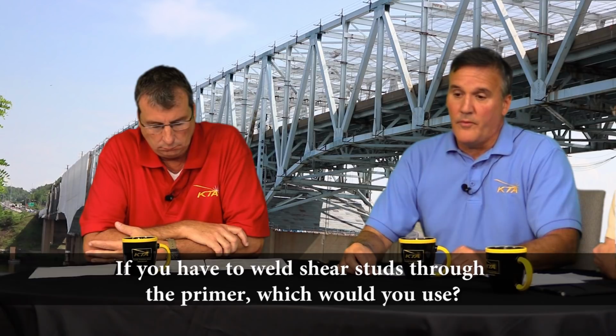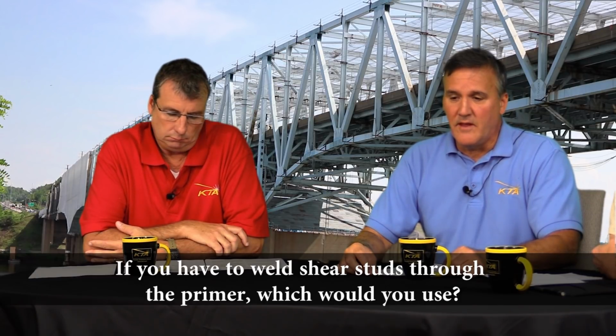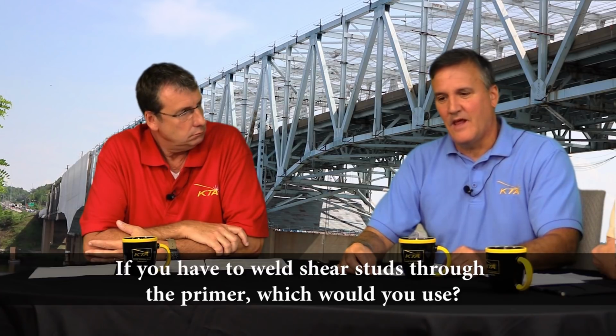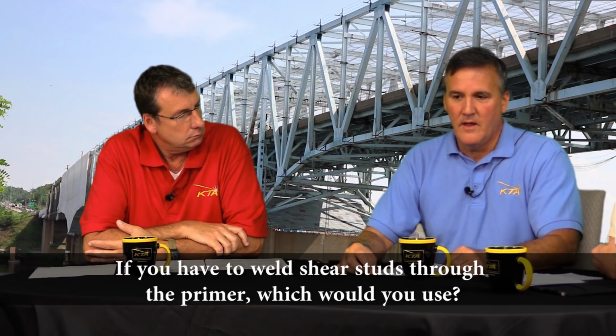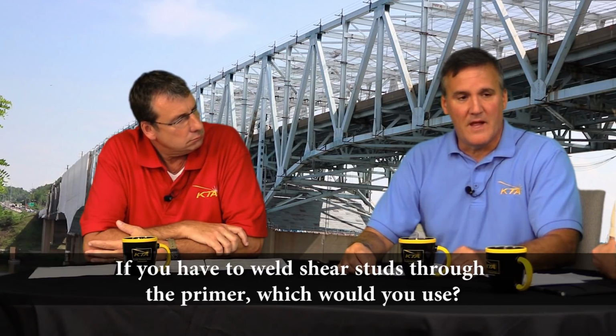Okay. All right, let me go to top flanges. Many times for bridge steel, you're going to put the zinc on the top flange only, and they want to put shear studs, attach shear studs. Which primer would you suggest in that case? Jim? Well, we see use of both, but a lot of it has to do with the sequencing of the work. If they're just exposing the top flanges and they're blast cleaning them and they're going to shoot shear studs on the top flange with only those areas exposed only, I would probably prefer to use the inorganic zinc to prime the top of the flanges that are going to have shear studs.